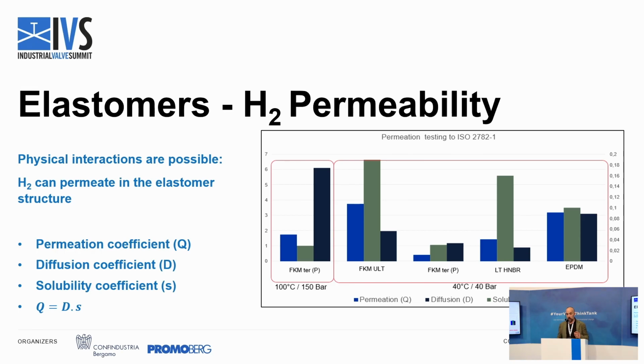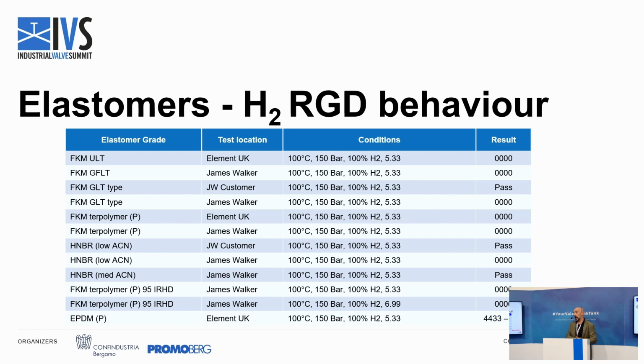But this permeation can lead to RGD damages, because if we have an elastomer compound with a gas inside and we depressurize, the gas tends to grow in volume, to expand, sorry, and that could actually cause RGD damages. So we ran a test campaign on 100% hydrogen with the Norsok conditions. So again, 100% hydrogen, 100 degrees, 150 bars. The pressurization rate is always between 20 and 40 bars per minute as per Norsok. We tested at 37.5 bars per minute.